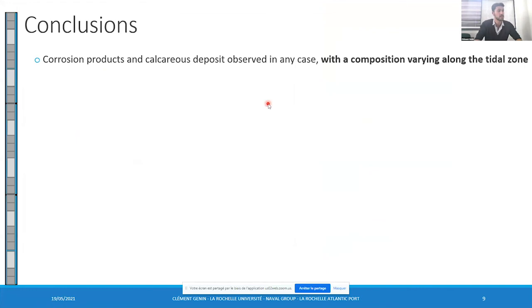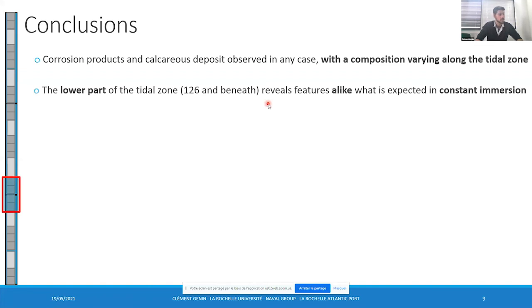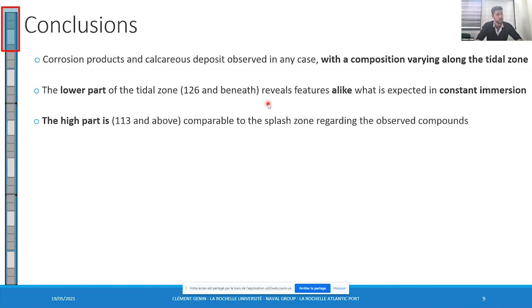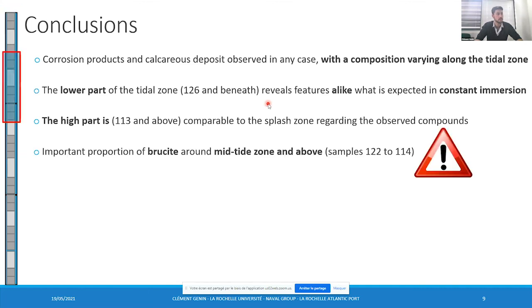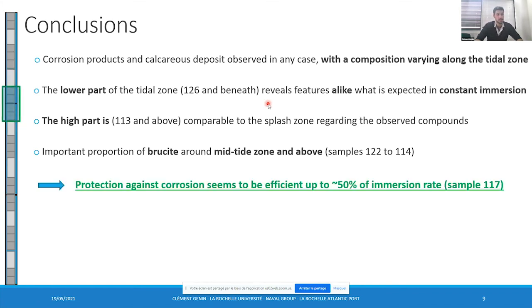To conclude, the varying composition of the mineral layer along the tidal zone is indicative of the varying mechanisms we encountered. The low part of the tidal zone is comparable to a constant immersion, while the upper zone is really similar to the splash zone. The key point of this presentation is that brucite has been detected here, which was not expected. Through this and the ratio of calcareous deposit above the corrosion product, we may assume that cathodic protection should be efficient up to 50% of the immersion rate in the tidal zone.